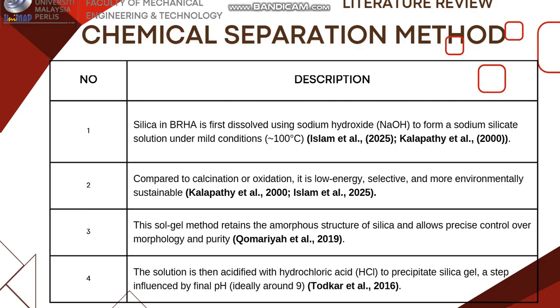Silica in BRHA is dissolved using sodium hydroxide to form sodium silicate solution at around 100 degrees. This method is low energy, environmentally friendly, and preserves the amorphous structure of the silica. Then hydrochloric acid is added to precipitate the silica gel, with pH control being a key factor in the process.